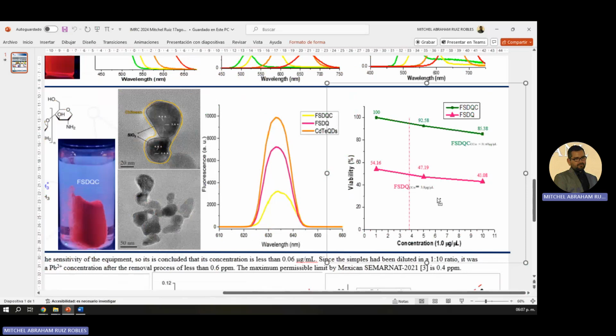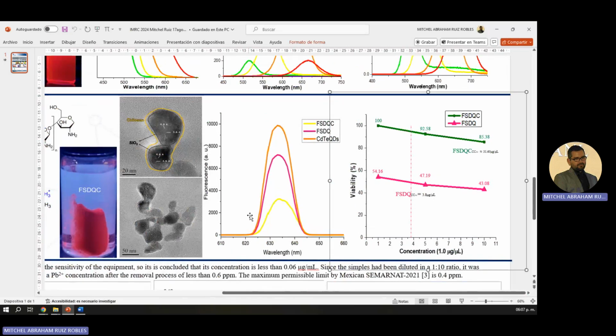The MTT assay, shown here, was carried out to characterize the viability of the nanocomposites with Caco-2 cells, showing an extraordinary viability percentage increase for the complete nanocomposite relative to the nanocomposite where we do not add chitosan, for concentrations up to 10 micrograms per microliter. And here we justified the usage of chitosan, shown in this graph: this pink line is for no chitosan and this green one is for using chitosan in the final nanocomposite.